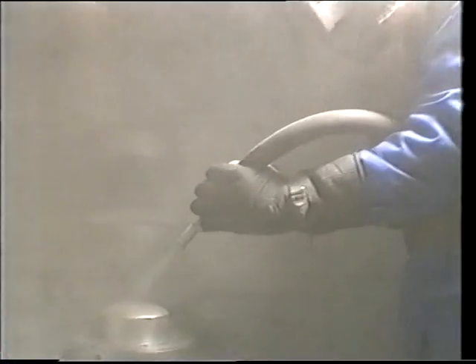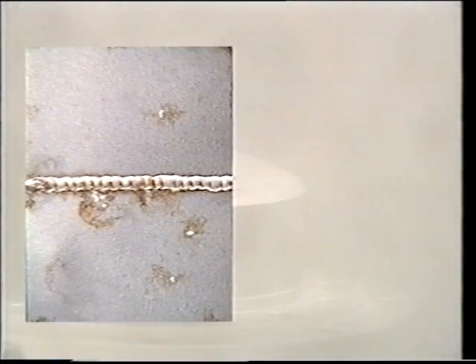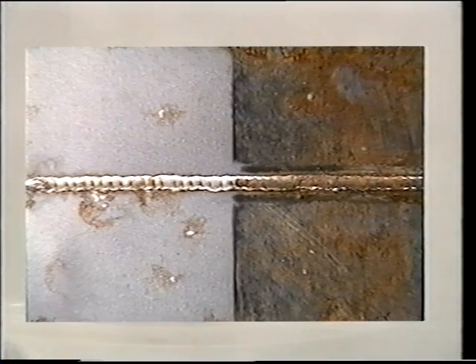On the other hand, however, detached oxide particles or glass fragments can damage the metal surface. The resulting potential differences lead to typical corrosion phenomena after only 2 weeks of exposure to an aggressive atmosphere. For comparison, here is a ground surface after the same treatment.